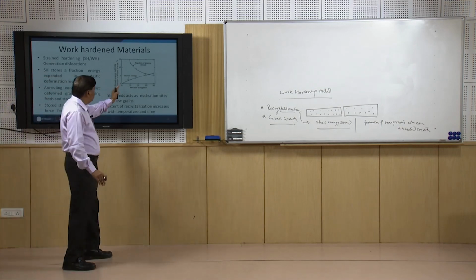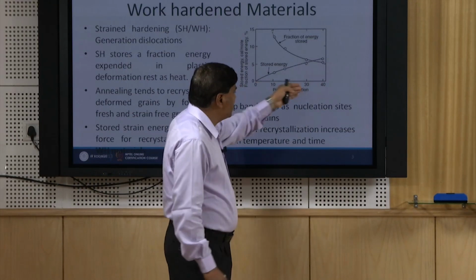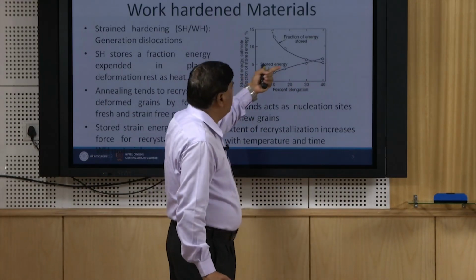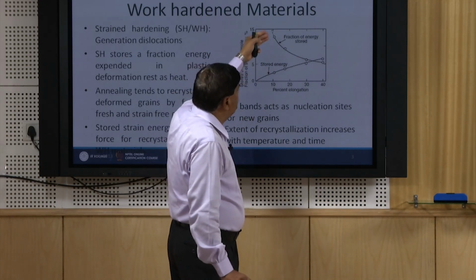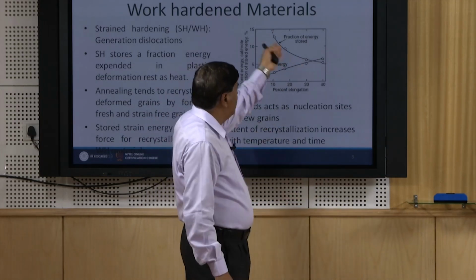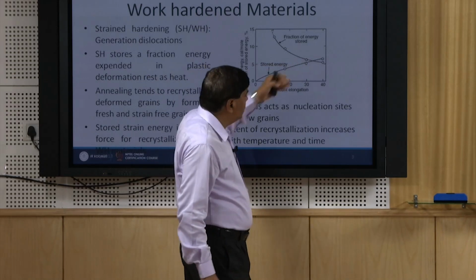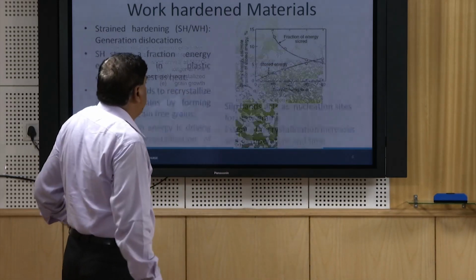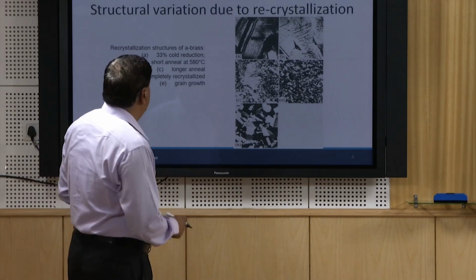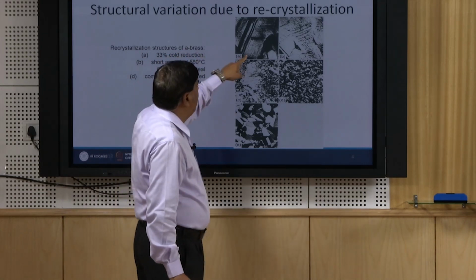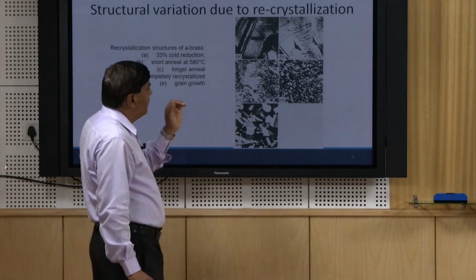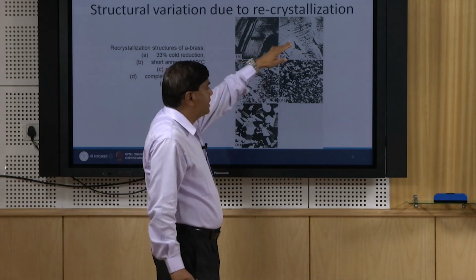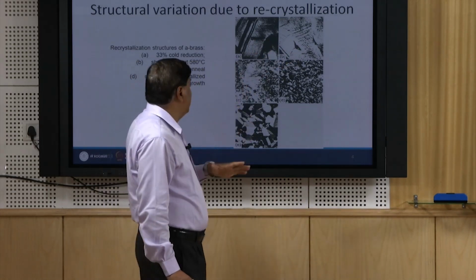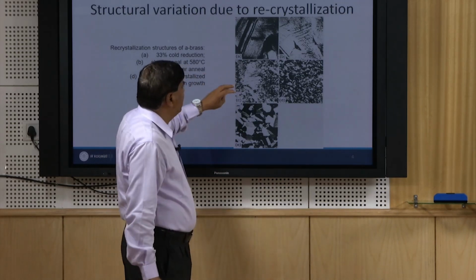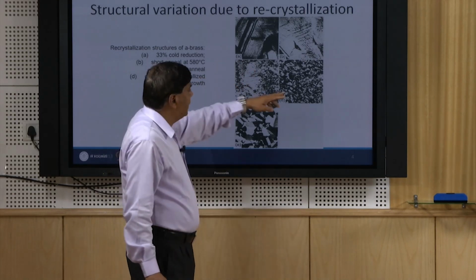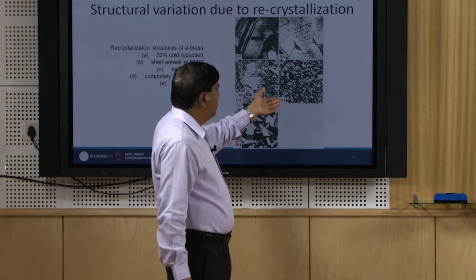So, here we know that as we increase the deformation, increase in elongation takes place, say increase in strain is taking place. So, the stored energy increases continuously and the fraction of the energy stored out of the energy supplied keeps on decreasing. So, this is what we can see, strain energy stored increases with the strain or the deformation which is being applied, and whenever heat is applied, the material in a very strained condition offers a large number of dislocations, and when the material is annealed for a short period, some of these dislocations are lost or annihilate, and further longer annealing results in the loss of these dislocations completely, and then complete recrystallization and formation of new grains take place with the continuous exposure at a high temperature,